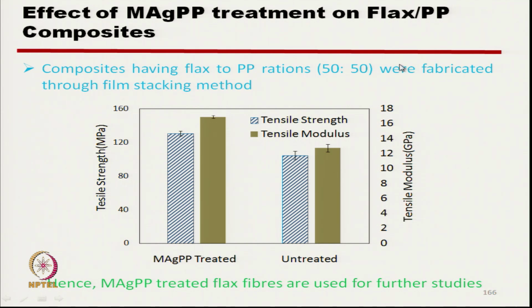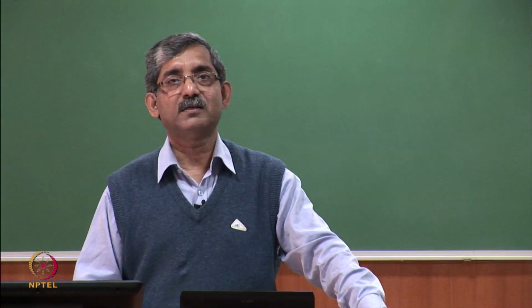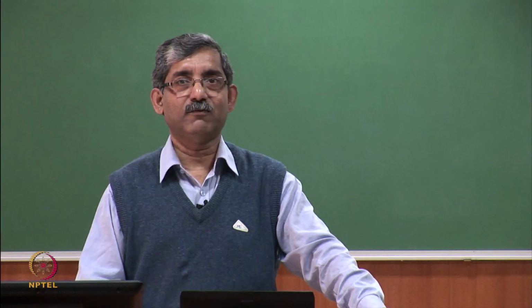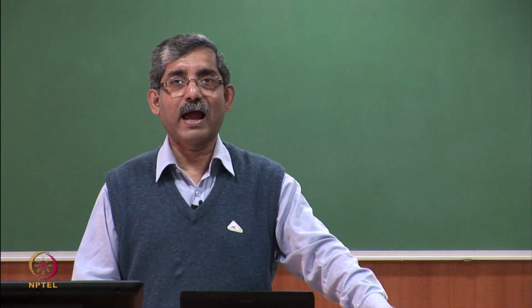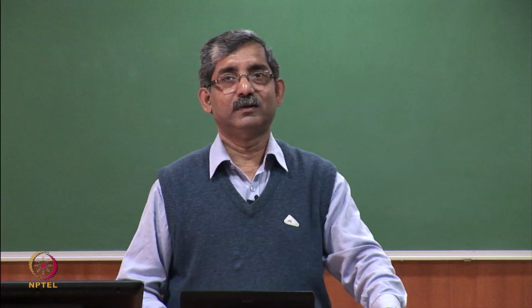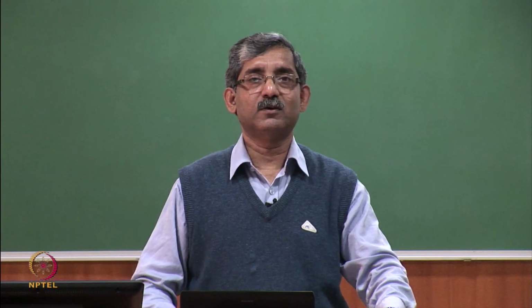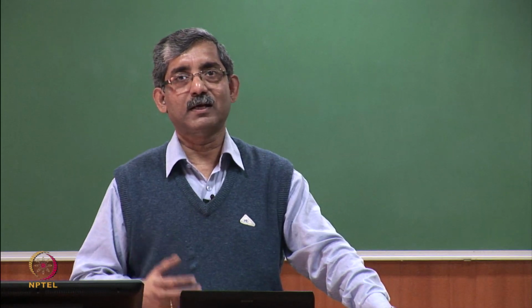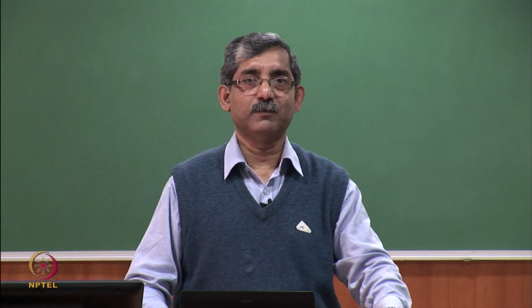Here we have used a 50-50 polypropylene and flax ratio, and we have fabricated the composite using the film stacking technique. This 50-50 ratio is at the composite stage. In the thermally bonded roving stage, we used 60-40, that is 60% flax and 40% polypropylene, and once we add extra polypropylene film in between the series of rovings, the polypropylene percent increases. So, ultimately it has become 50-50.